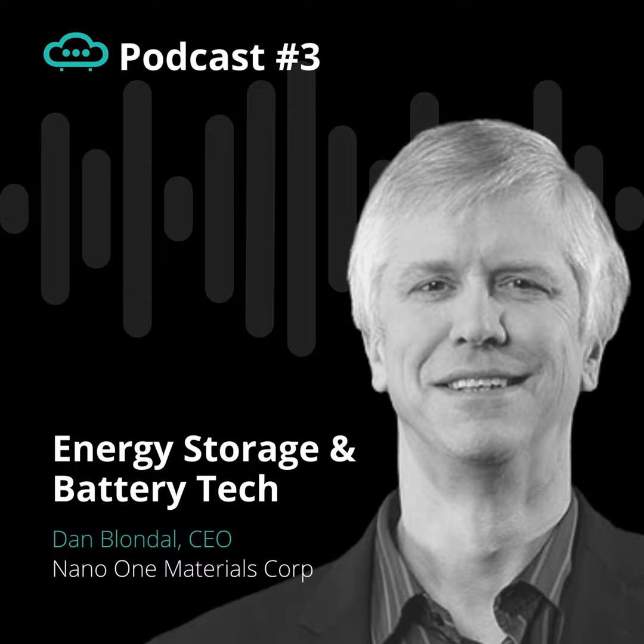How that differs from the way industry makes them today: industry will tend to make a larger, hard, crunchy ball of lithium, nickel, manganese, and cobalt. If you break it open, there are crystals in it, but they're all faceted, so there may be hundreds or thousands of little crystals stuck in there with grain boundaries between them. Those grain boundaries are where the cathode material fails. As you crush it onto the foils before you assemble the battery, those balls break open. As you cycle the battery and move lithium in and out, the crystals swell and contract, because lithium causes the layers to push open a little bit, and as you pull it out, they shrink. That causes stresses along the grain boundaries, and they crack even further open. That exposes everything inside the particle to side reactions within the battery.